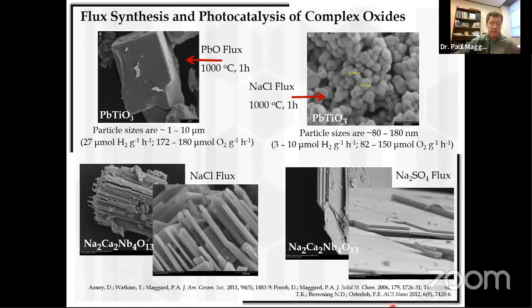So in this case, the below case with a layered structure is the example where if you shorten the path length to reach the surface, you get a much higher activity.